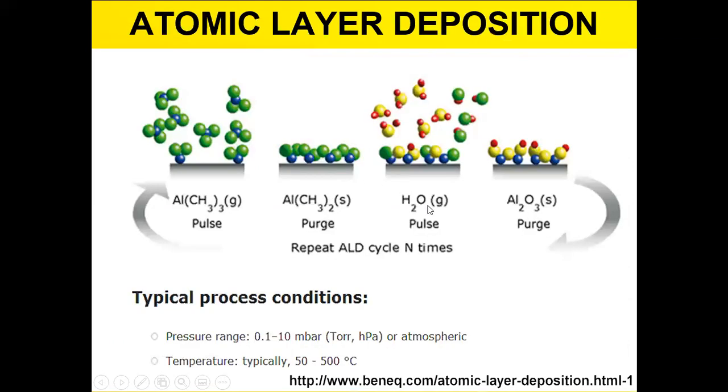Atomic layer deposition is a technology that is becoming more and more mature. The process is basically to put a precursor down, which only one atomic layer thick will adhere to the surface that it's coating, but it's conformal. Any exposed surface will be coated.